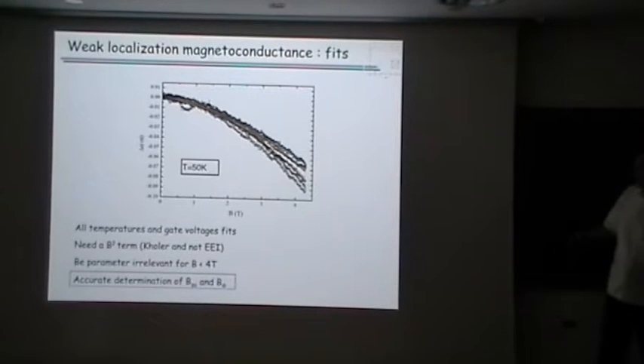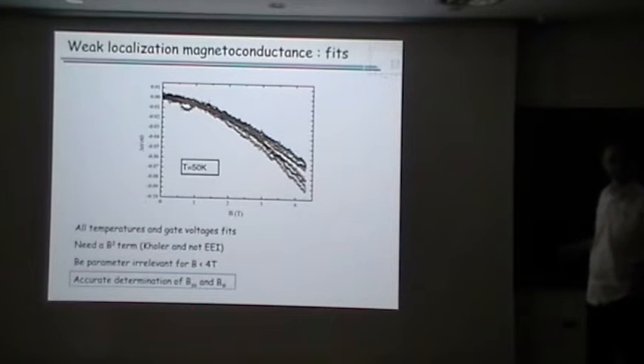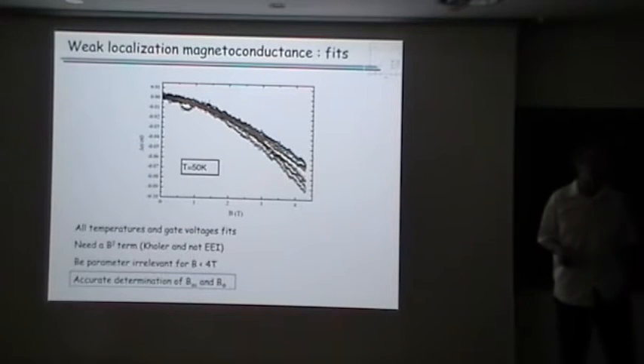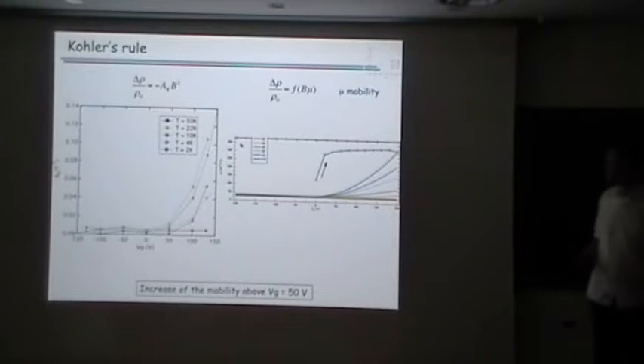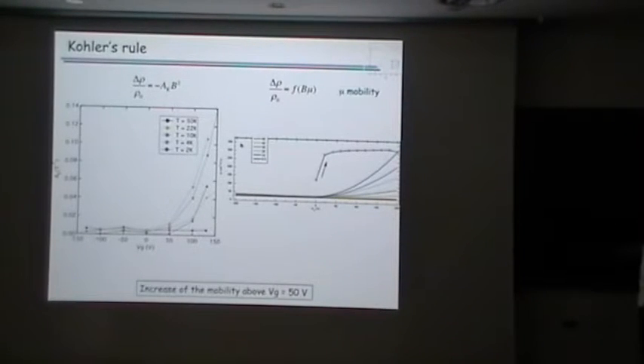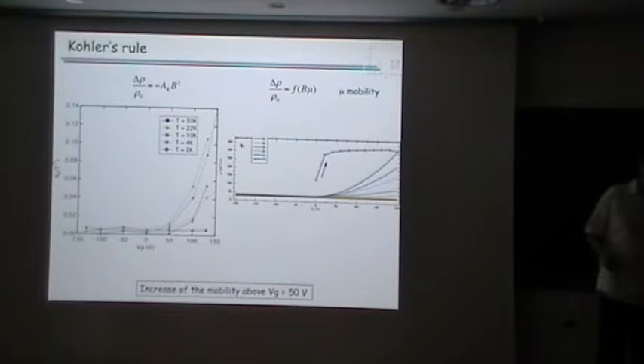So we can have this parameter, the spin orbit, which is the inverse of the spin orbit scattering time, and B phi, which is the inverse of the inelastic scattering time. First of all, we have this Kohler coefficient here, A. What you see is that at high temperature it's constant with the gate voltage. But at low temperature, it rises up. This is not a surprise, because the mobility also is rising, and Kohler's rule is related to the mobility. So nothing fancy about this fact. That means that it's valid to use this parameter in our field.